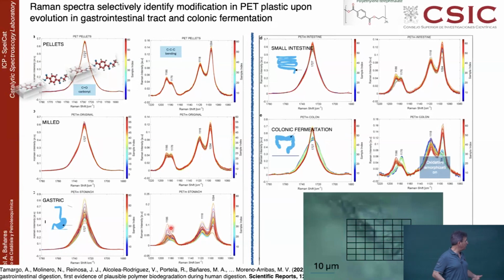And then when it goes to the colonic fermentation, you even see much more changes, and even some of them, like the relative intensity of this band here that was very constant on the fresh system. Here you can see that the relative intensity changes a lot, and even that peak almost disappears in many positions. This is telling you a very major degradation of the PET within the colonic fermentation. Also here, you see changes in the crystallinity of this polymer. Polymers tend to be semi-crystalline with regular structure, like in this drawing there, like a plane, very regular. So the body is affecting the plastic.